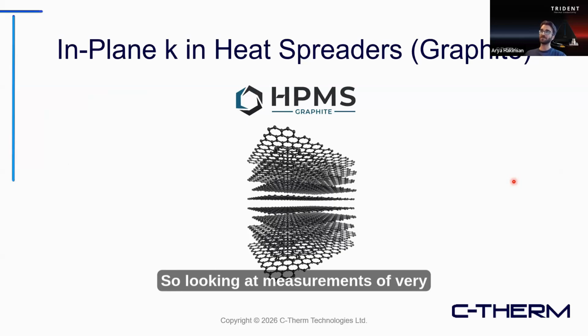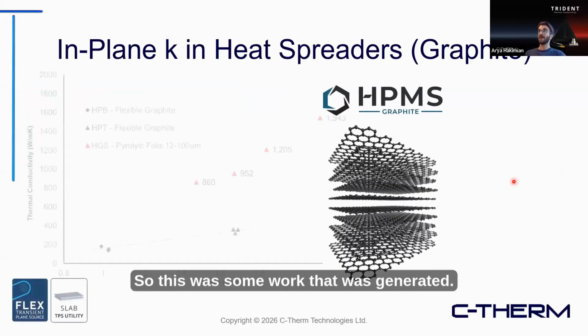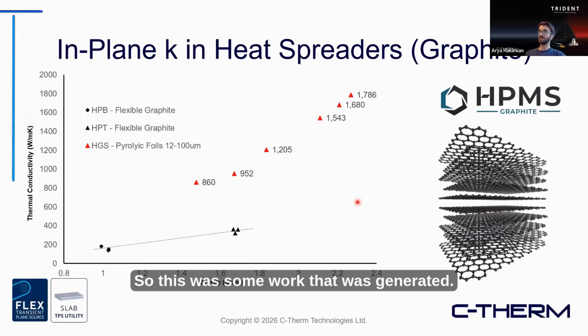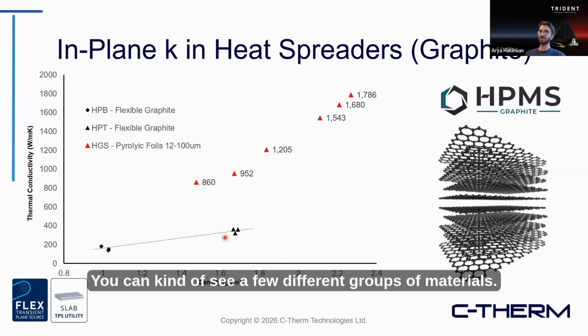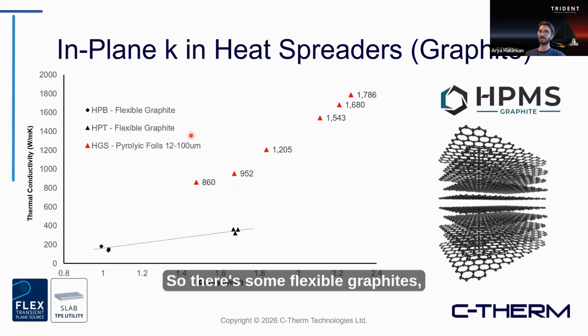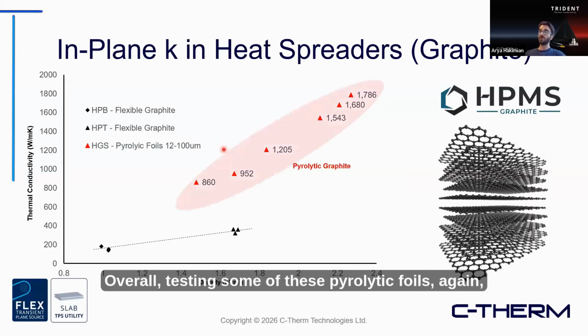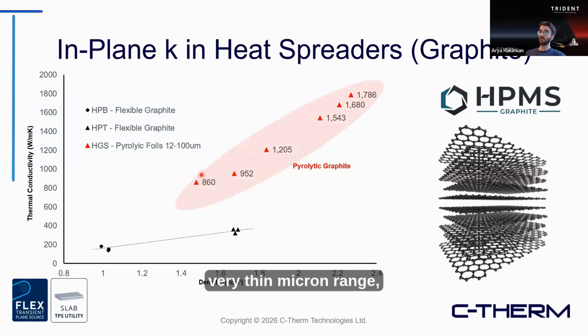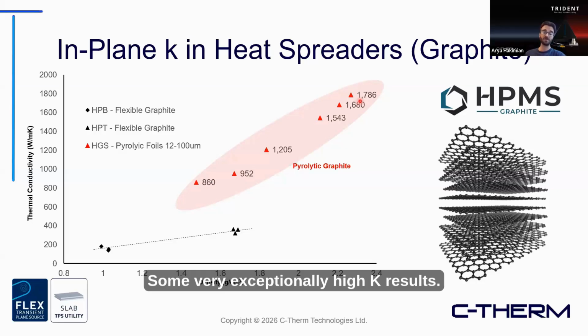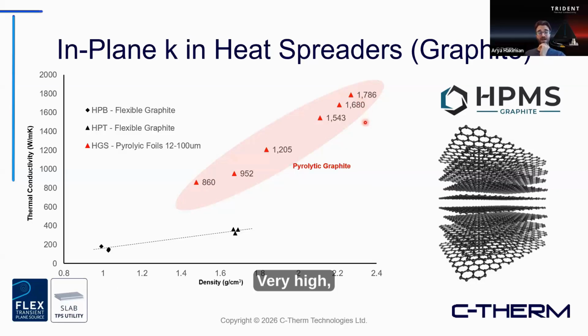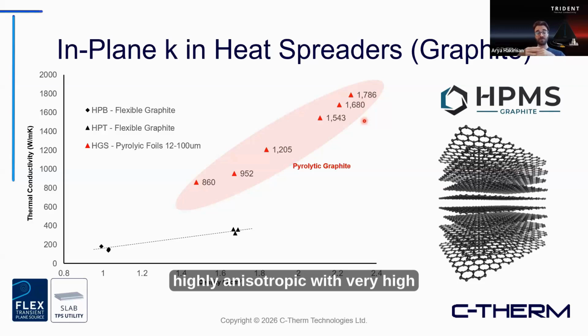So looking at measurements of very conductive, very thin graphitic materials. So this was some work that was generated. You can kind of see a few different groups of materials. So there's some flexible graphites, flake style, versus some pyrolytic foils. Overall, testing some of these pyrolytic foils, again, very thin, micron range, we were able to get some exceptionally high K results.